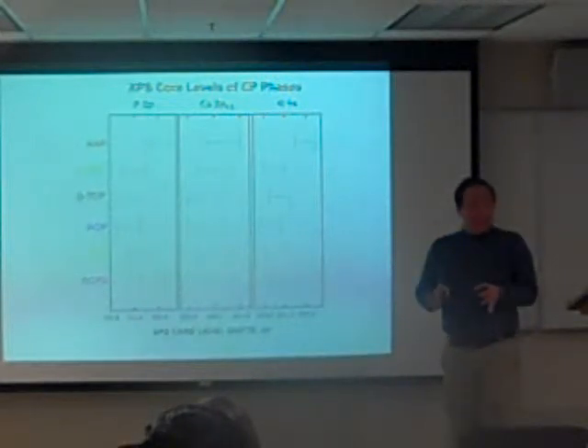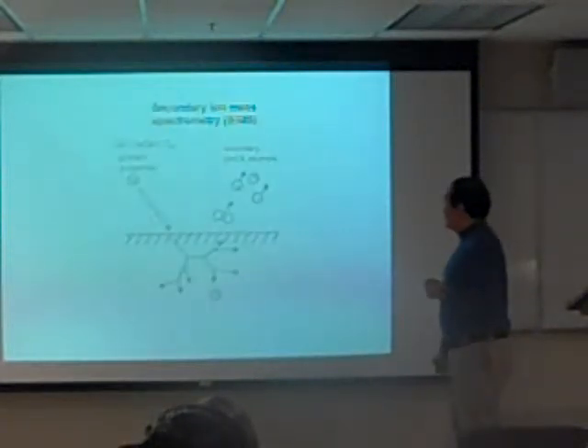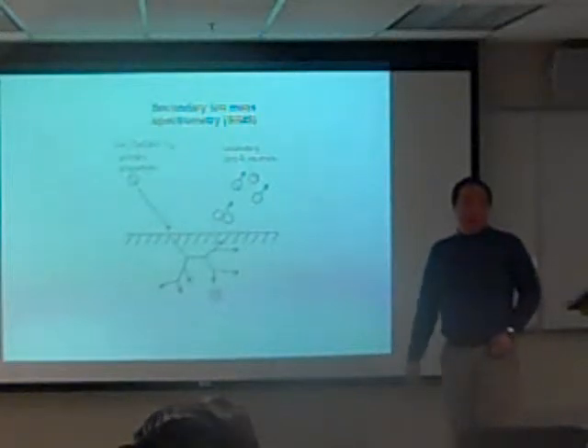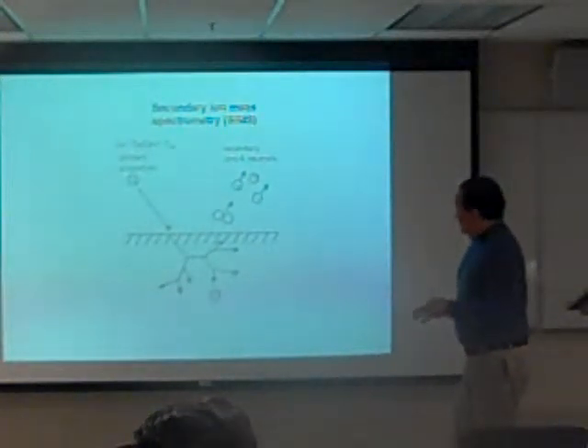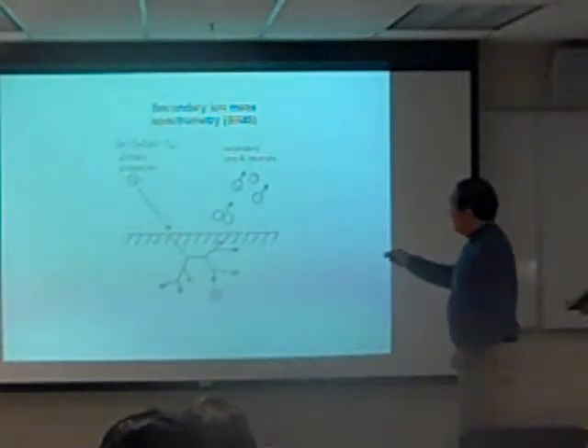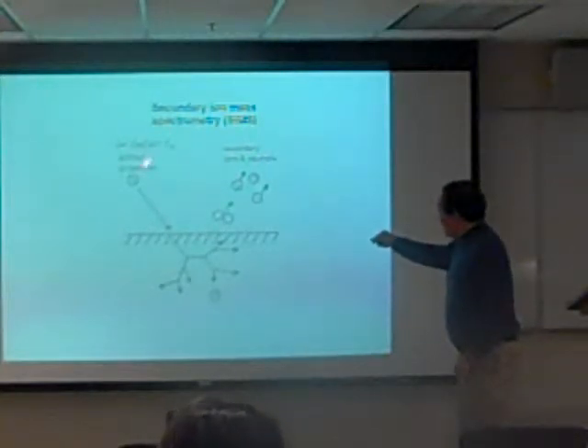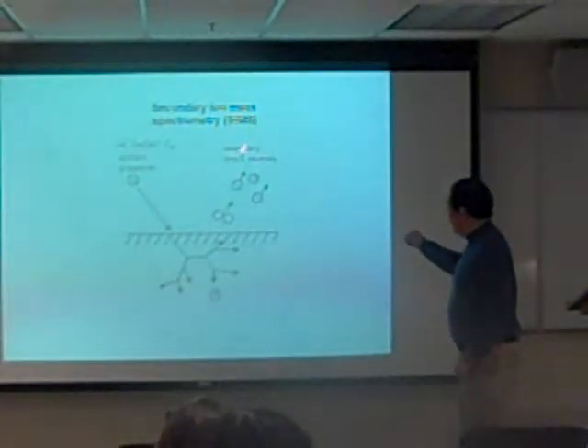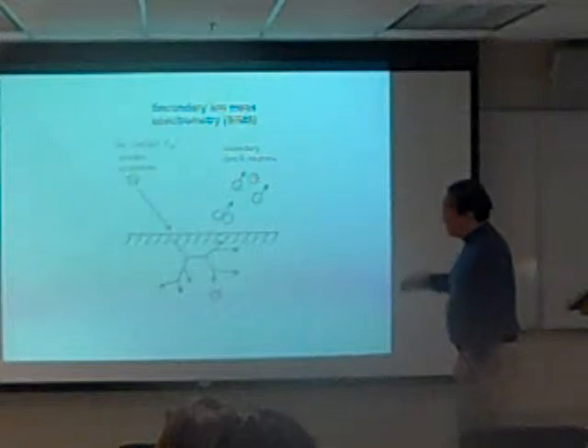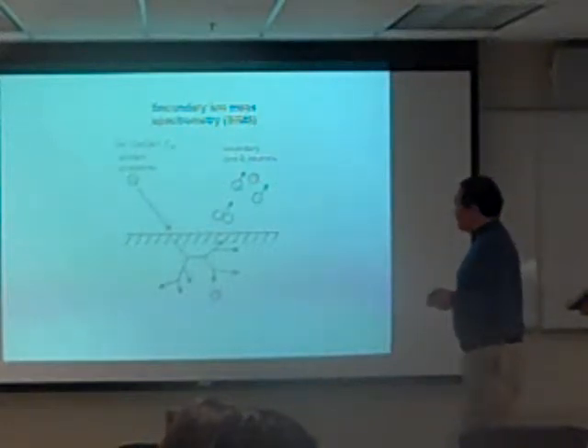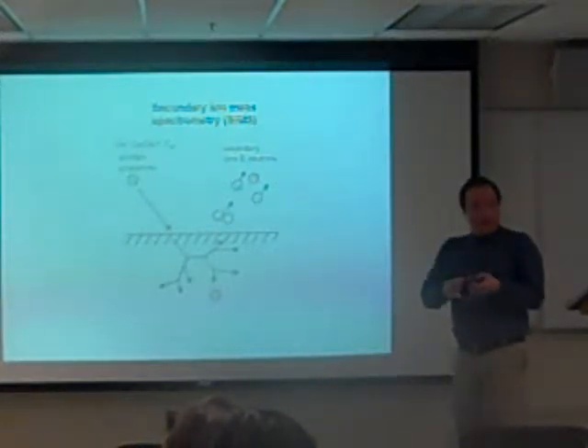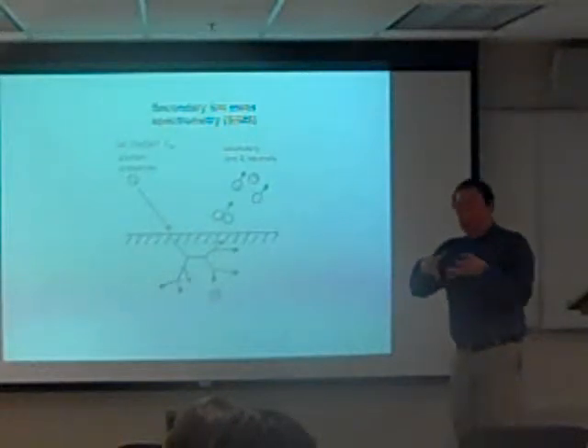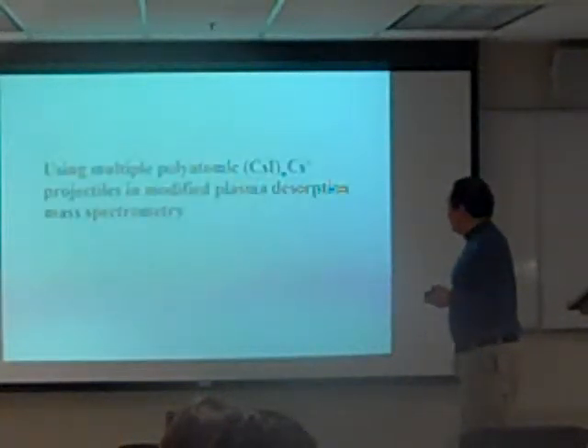Okay? So basically, XPS wasn't the only thing that we used. We also used secondary ion mass spectrometry. This technique is based upon bombarding the surface with primary projectiles that results in the release of secondary ions and neutrals, which can be detected. And then again, that could be used as a way of fingerprinting the type of phase that forms.